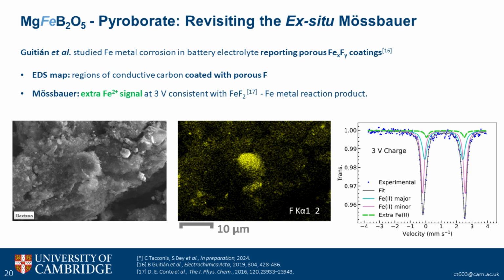And what we found was a study by Gutian et al., who saw that they were forming porous iron fluoride coatings throughout the first charge when they were studying the iron metal corrosion. So what we did was we went back to look at our EDS maps, and we found regions on the conductive carbon surface, which are very distinct to our cathode phase, that were coated with a lot of fluorine. And we also looked at the Mossbauer.